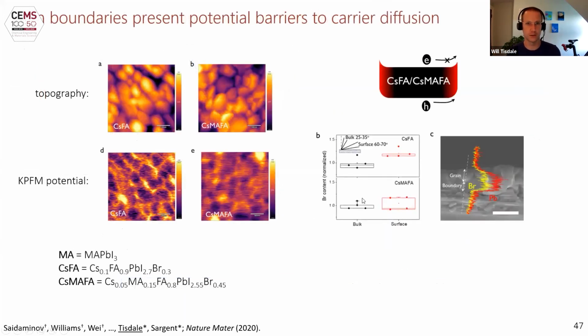The evidence that I glossed over or neglected to discuss at all are these Kelvin probe force microscopy measurements. So here's the AFM topography map of the binary cation and the ternary cation. And then the Kelvin probe force microscopy measurement is showing, at the lowest level, greater differences between the grain boundaries and the grains in the potential in the binary cation than in the ternary cation. It's a more homogeneous landscape, which led to the hypothesis, okay, that these grain boundaries are acting as potential barriers. Some evidence for that came from this angle resolved electron emission experiment, where we're trying to get some depth sensitivity by looking at different angle emission of photoelectrons in this case. And we can map differences of, yeah, I honestly can't remember what that figure is trying to show.